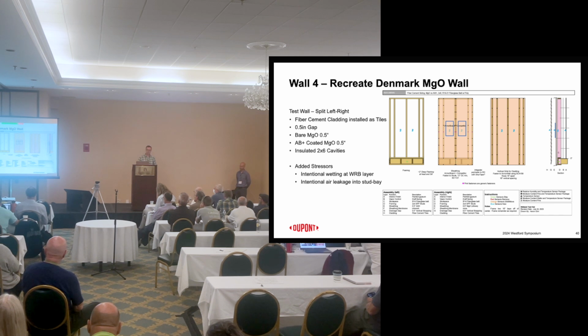But this one, we wanted to recreate the Denmark one, and one of the issues with Denmark was the height of the cavity, and we didn't want to play with that. So I didn't do a horizontal split on this one. I did a vertical split. And then what we did on this one is we took the bare MgO product, so we did what they did in Denmark, and then one right next to it with the coating on it, the WRB coating.